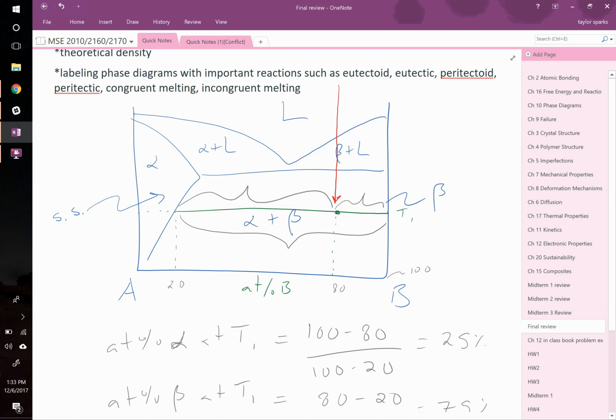But you'd say, okay, just above the eutectic temperature, what does a microstructure look like? And you'd say that's easy enough to do. You could do the lever rule, but it's about a 50-50 mixture, because you're going between that point, this point, and that point. These should be touching. So that's about a 50-50 mixture. So you'd say there's 50 volume percent globs of the beta phase floating in liquid. You could tell me that the liquid has the eutectic composition, whereas beta phase is basically pure B.